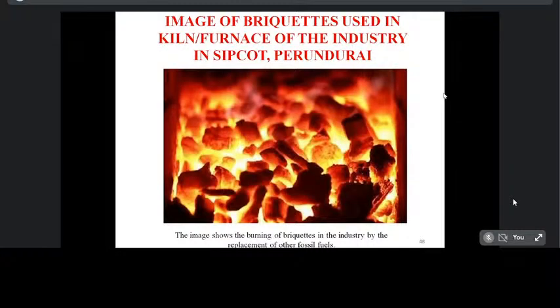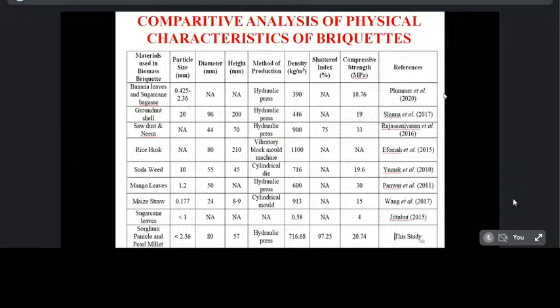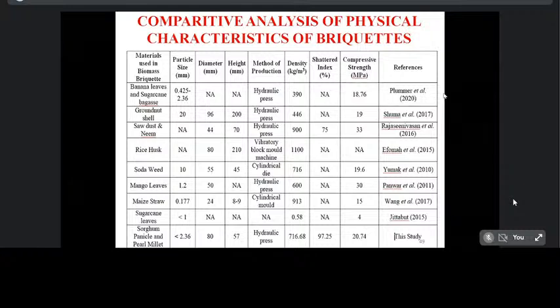kiln furnace of the industry in the SIPCOT area, while burning the produced biomass briquette in the particular industries. So the comparative analysis of the physical characteristics of briquettes: previous studies used various materials with various particle sizes. The particle sizes range from 0.425 mm to 10 mm; here we have taken less than 2.6 mm. The diameter also varied from 24 mm to 96 mm, and the height of the briquette varied from 8 to 9 mm up to 210 mm.